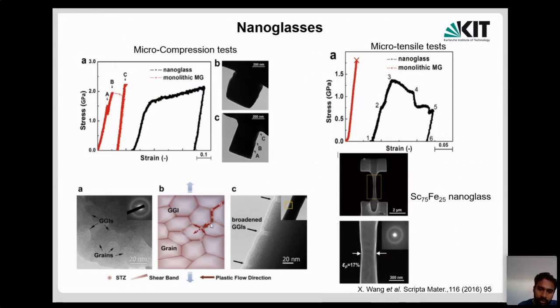And when you have such kinds of interfaces, these interfaces can be nucleating sites for the shear transformation zones, which I talked about. So these are disordered regions. They're loosely packed, so they can move. So you can generate a lot of shear transformation zones, and this lot of shear transformation zones can give you enormous ductility, which is also what is shown with the tension curve here. Tensile dog bone specimen, you see there is some necking here, like 17%. So this is quite an interesting observation from nanoglasses. By changing the composition on a very nano scale, like 10 nanometers or so, you can generate such kinds of properties.